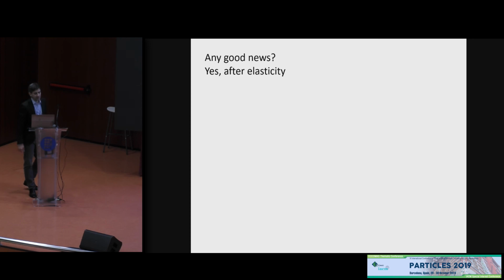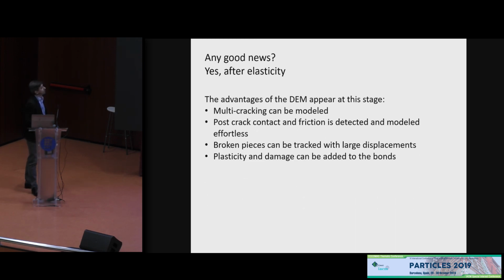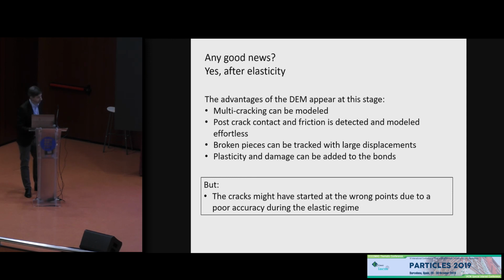So after that, are there any good news? And we think that after the elastic range, there are very good news, because the advantages of the DEM appear at this stage. You can have multi-cracking, and after the cracks, the contact and the friction are detected very easily, and it works very well. The broken pieces can be tracked with large displacements, rotations, etc., and you can add plasticity, damage, whatever you want on those bonds. So we should solve elasticity as best as possible. Of course, the cracks might have started at the wrong points due to poor accuracy during the elastic region.